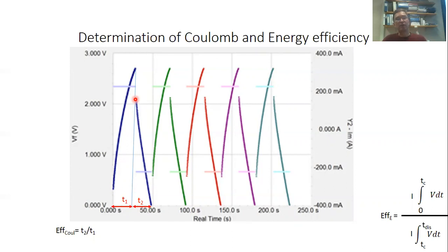Therefore, just the ratio of the integral underneath the discharge curve and the integral underneath the charge curve gives me my relative energy efficiency in percent.